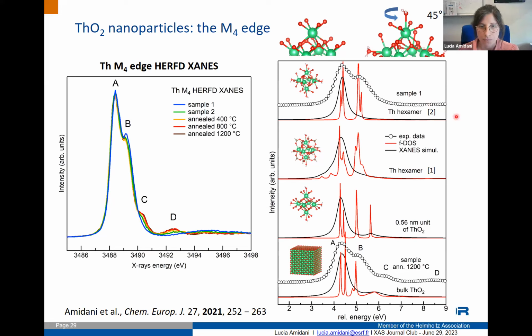So this is to say that basically the information we got from the PDF was fundamental to understand what we see in the M4 edge, and what we see in the M4 edge is compatible with the presence of those clusters.